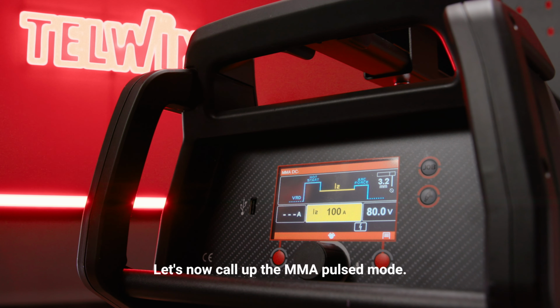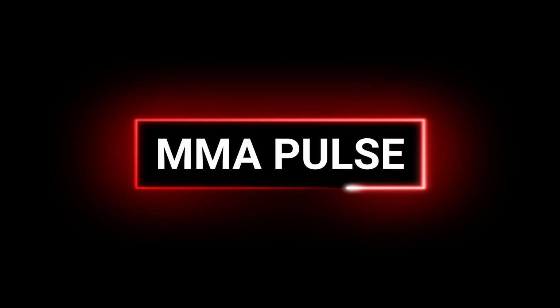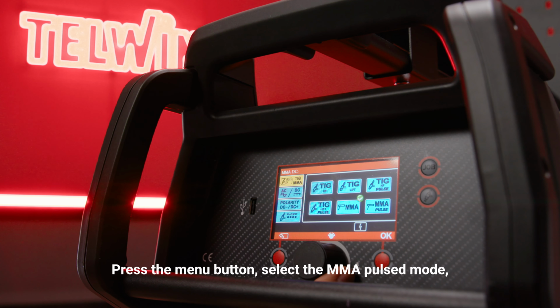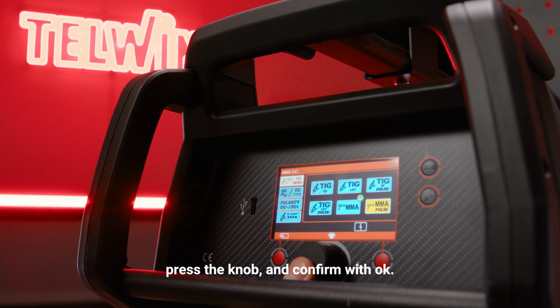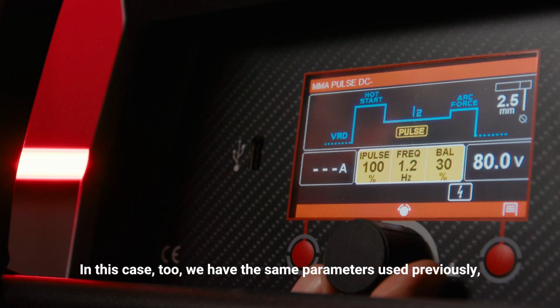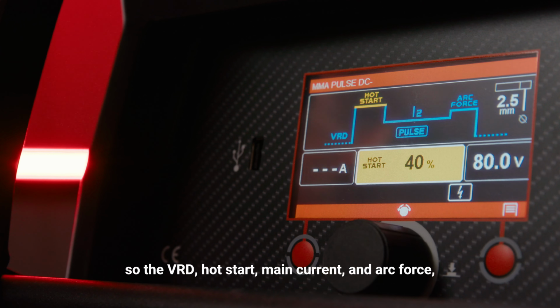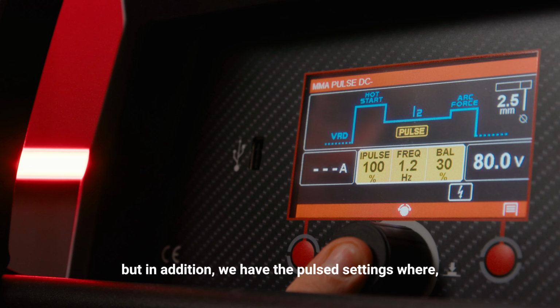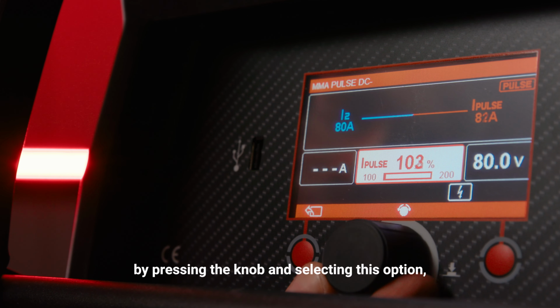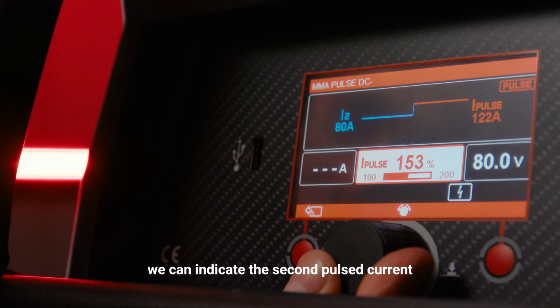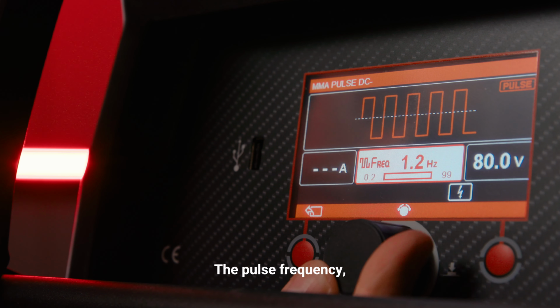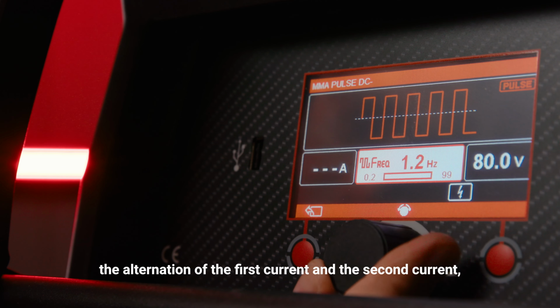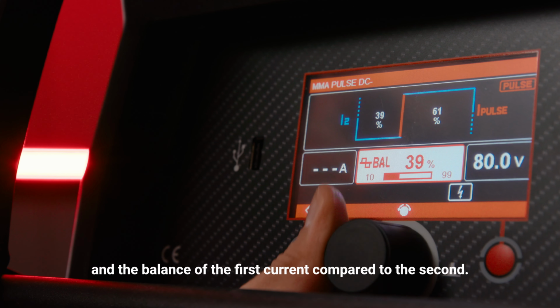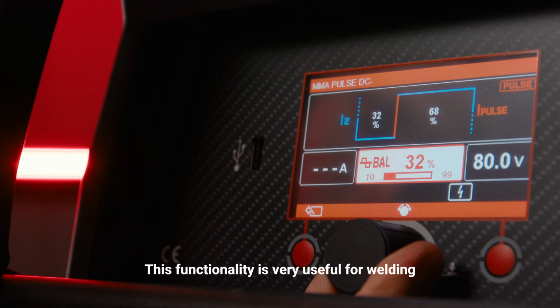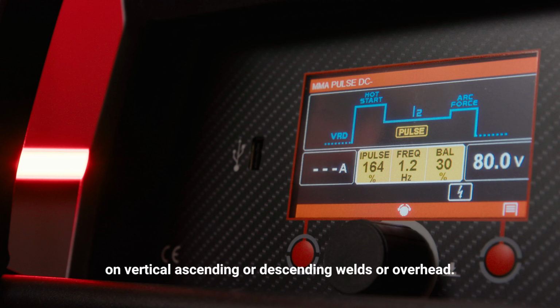Let's now call up the MMA pulsed mode. Press the menu button, select the MMA pulsed mode, press the knob, and confirm with OK. In this case, too, we have the same parameters used previously, so the VRD, hot start, main current, and arc force. But in addition, we have the pulsed settings where, by pressing the knob and selecting this option, we can indicate the second pulse current that must be higher than the first. The pulse frequency, the alternation of the first current and the second current, and the balance of the first current compared to the second. This functionality is very useful for welding on vertical, ascending, or descending welds or overhead.